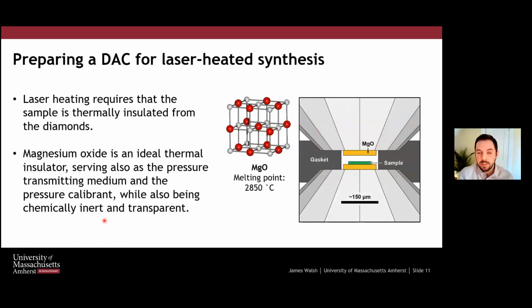Okay, if we're using laser heating, then we have to do something special with our diamond anvil cell, which is to insulate the sample. And we do that by using magnesium oxide. Magnesium oxide allows us to basically sandwich our sample between two pieces of magnesium oxide. I'll show on the next slide how we make those. But this is ideal because it serves multiple purposes.